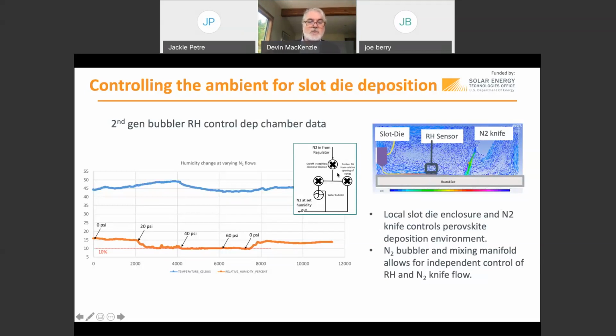We made water-saturated nitrogen and mixed that with dry nitrogen, feeding it in at different rates to flow the environment over the knife, and we really control that quite well. With these different flow rates, we're trying to control at 10% within a couple of 1 or 2% RH, which is about as good as you can really hope to get. We are able to control extreme excursions when the outside Seattle weather gets to 80% RH externally. We can also use intermediate room control. We can put rough dehumidifiers in the overall processing lab that bring it down to maybe 50% RH, 40% RH, something like that. Then the local box fine-tunes what we want the humidity to be.